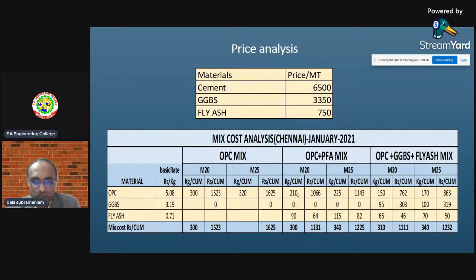For the OPC customer, PFA customer, he uses 210 kgs of OPC and 90 kgs of fly ash, right? So the mix cost comes to 1,131. Similarly, for M25 grade, he used 225 kg of OPC and 115 kgs of fly ash, total 340 kgs of supplementary cementitious material, and the price comes to 1,225. Whereas the triple blend is another form where we use all three materials.